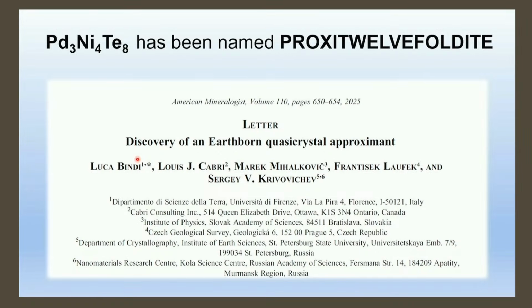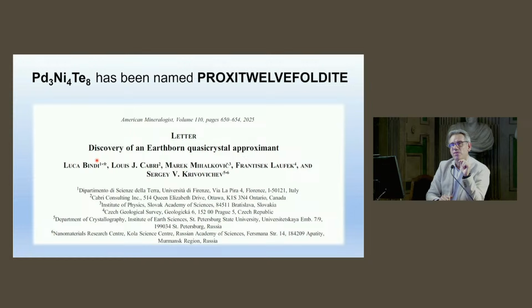So this is the composition. This is actually important because in this system there are no reported approximants or quasicrystals. So it's a system which should be investigated, especially because if you change the ratio between these elements, you can also find quasicrystals in this system.